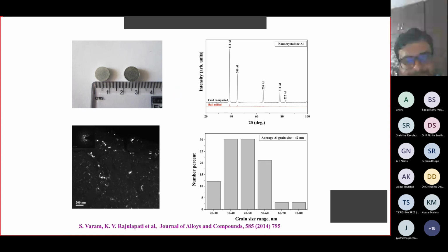So when we make materials using ball milling and then subsequently compact, they look like this. This is about 1 centimeter in diameter and roughly slightly more than 1 centimeter in thickness. So we made these small discs, and making a larger sample than this is difficult in this process. And we call them bulk samples because when you compare the size of the sample to the microstructure length scale, see here, this is a dark field image obtained using TEM. This length is 200 nanometers. These white regions are grains, and when we measured the grain size using statistical analysis, it shows that the average grain size is about 42 nanometers.